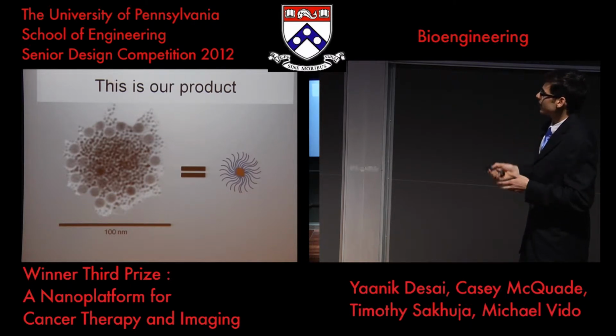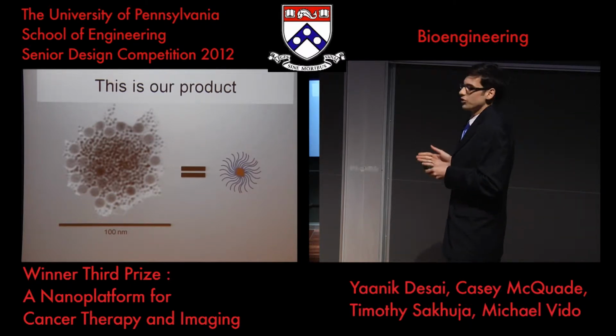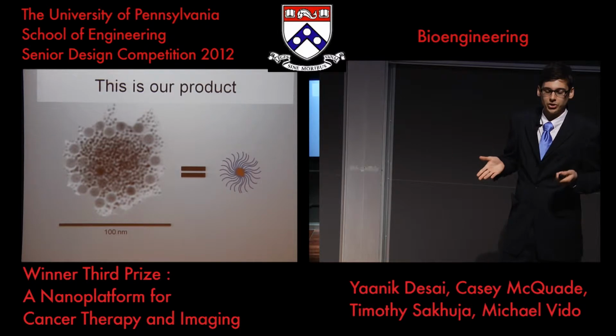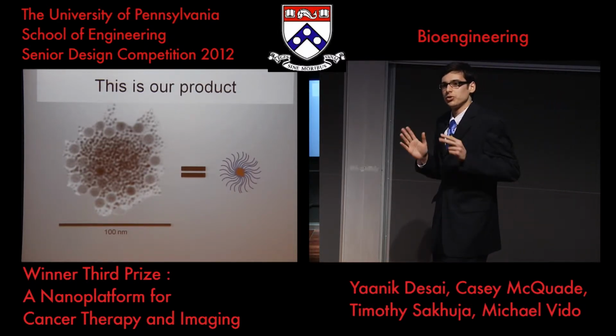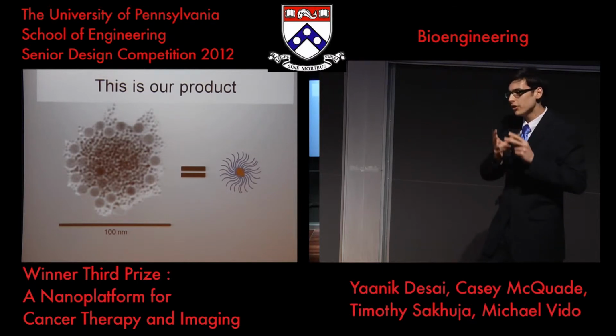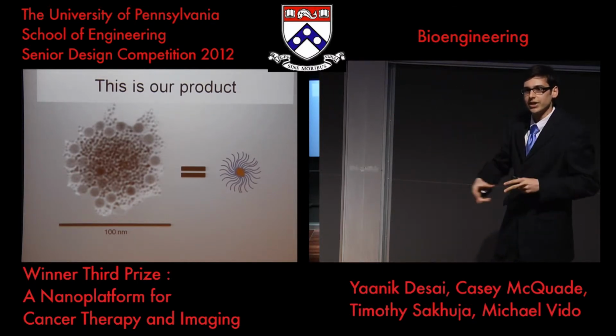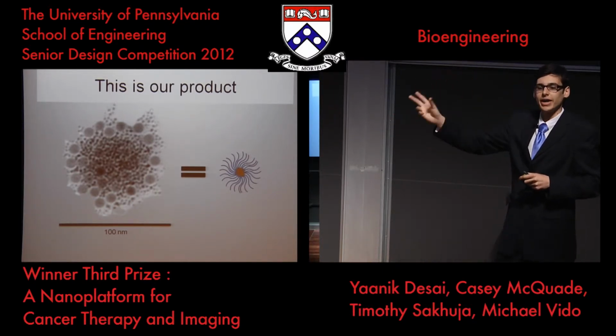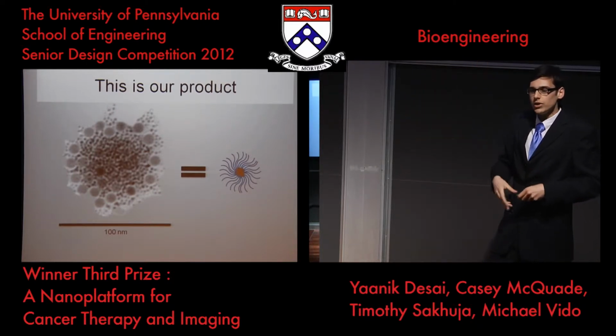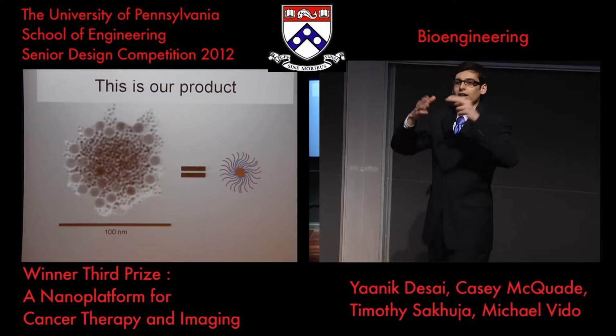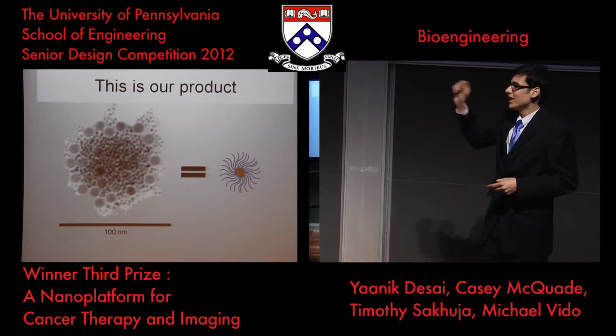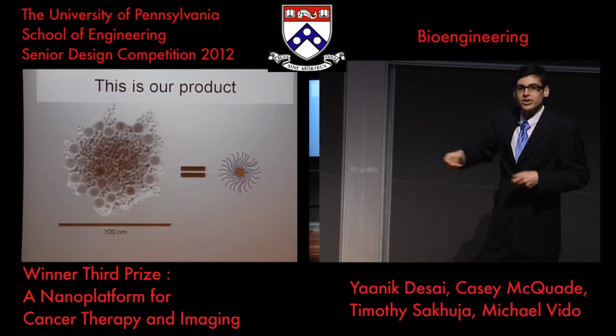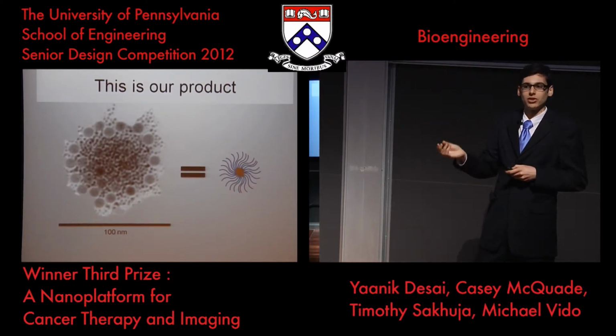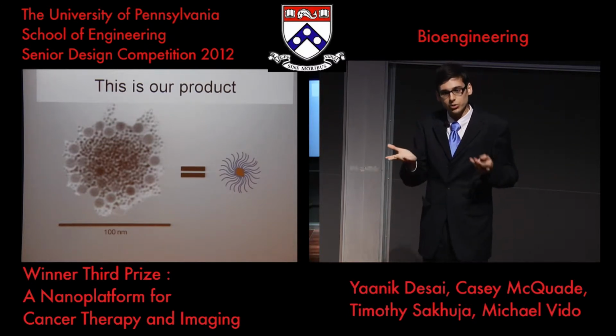So our optimal Micelles had a mean diameter of 100 nanometers, and this is to ensure ideal biodistribution properties. Micelles make really convenient platforms for drug delivery in our case, because they deliver both of our products simultaneously to our target and keep them there long enough for them to do their effects. Now, once we're done with them, we don't want these hanging around in the body forever. So the body can begin to degrade these biodegradable Micelles, releasing these really tiny particles into the bloodstream where they're quickly cleared through the kidneys, which is great.